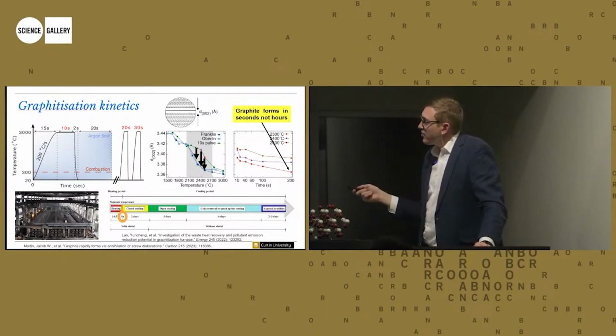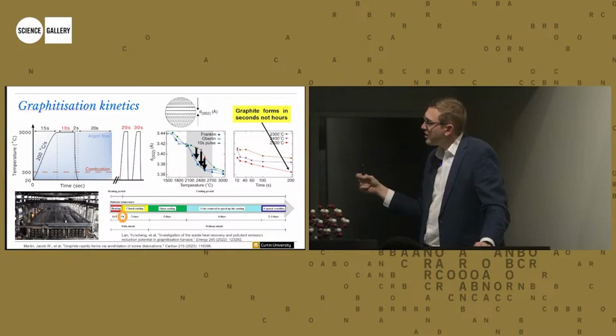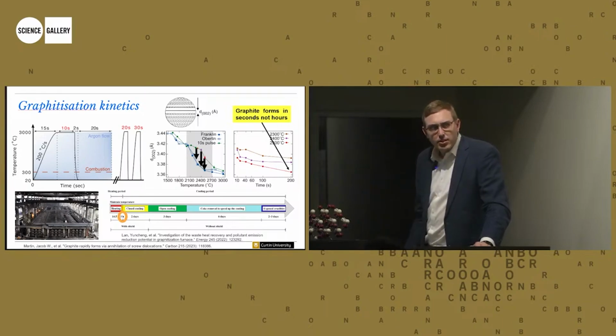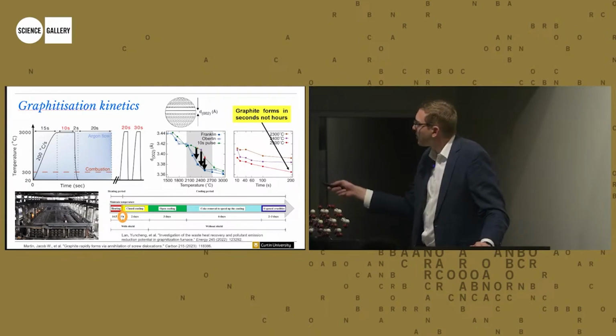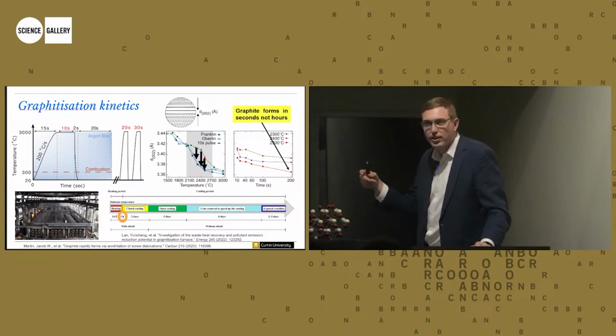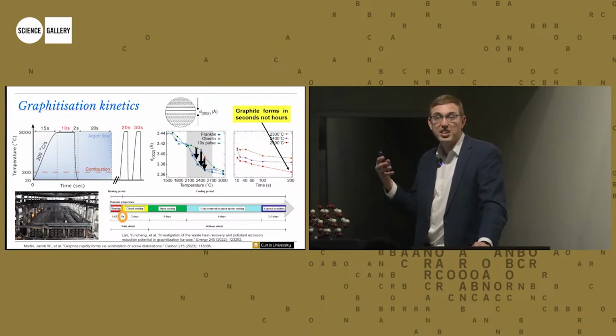Industry who was there, who makes graphite, looked at this plot here, which is the time that the layers go to the graphite spacing, and they said 200 seconds. That's really quick. And then this is only at 2,500 degrees. How fast does it form at 3,000 degrees? And I said, well, we can't measure it because it's less than 10 seconds.